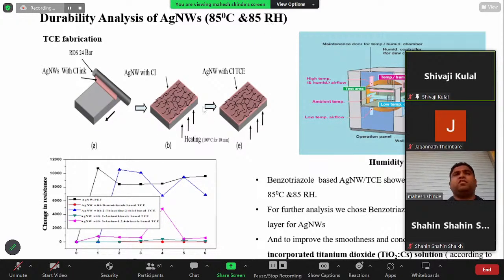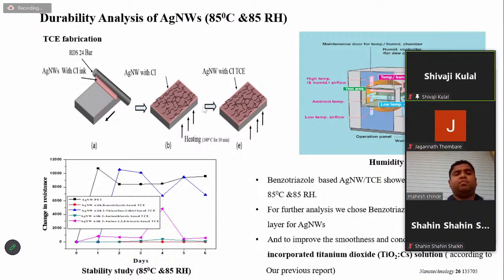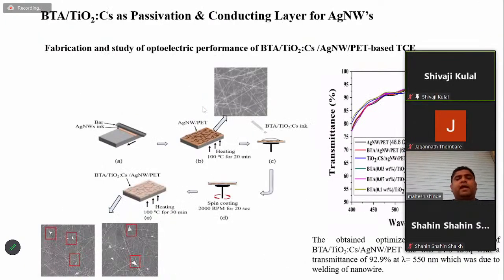from corrosion. So we found that benzotriazole is the best material, but we need to optimize it to get the proper sheet resistance, highly conductive with high transmittance. For that, I made different compositions, putting 0.03, 0.07 and 0.1 weight percentage BTA, and mixed it into the silver nanowire ink. I used a simple technique, wire bar coating.